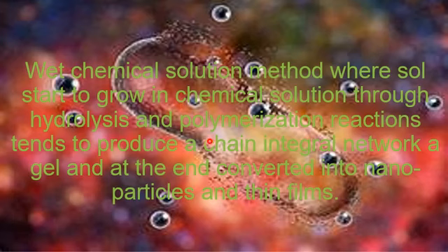Okay, and then the solution of the precursor is activated by the addition of an acid or base. So the chemical reaction is activated in the sol gel process, and most commonly hydrochloric acid is used, whereas sometimes potassium hydroxide is used to activate the chemical reaction.